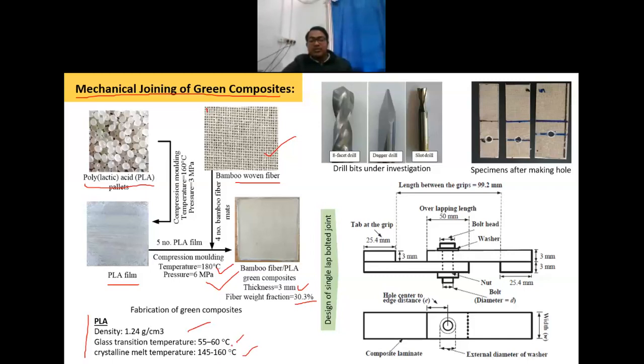Now these are the PLA properties like density, glass transition temperature, and melting temperature, you can see. The temperature of compression molding we have considered is higher than the melting temperature of the PLA, because we want to melt the polymer so that it can easily impregnate the woven fiber mat, and there will be better consolidation of the composite plate. So this is the composite plate we have created. Then we have prepared our specimens. These are the specimens you can see,